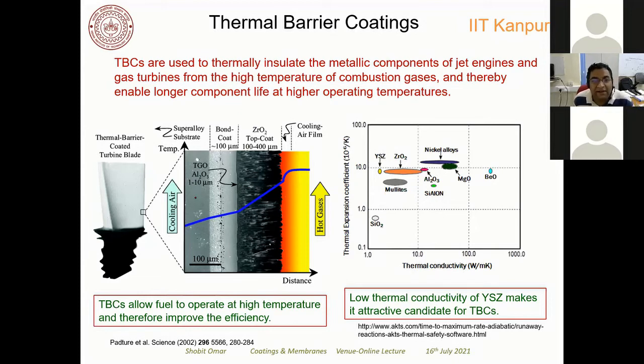So we have to protect these superalloys, and we do that by coating with the bond coat as well as some type of oxides. Right, the bond coat is basically 100 micron, and it contains chromium, aluminum, yttrium, right? As it's an alloy, it is oxidation resistant, while zirconia provides the thermal barrier. You can say the maximum thermal barrier that you can get is from the top coat of zirconia, and we use zirconia because it has low thermal conductivity, and it has a very close thermal expansion coefficient to the superalloys. So that will not spoil the top coat of this TBC when the temperature changes.